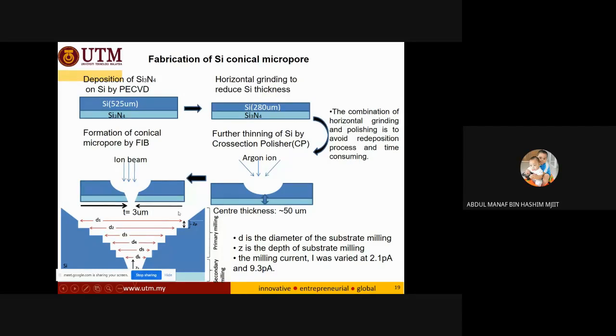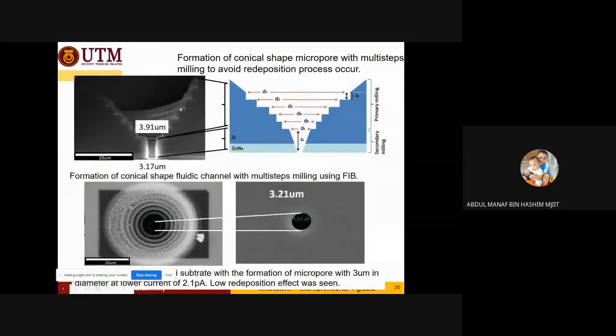Okay, so for the silicon micropore, of course we use FIB here. Let's say we have a sample substrate of silicon and silicon nitride. First we do a thinning and then a polishing, and then we get this structure. Then we proceed with FIB to get the conical shaped micropore. This is an actual fabricated conical shaped micropore. It is a two-step process: first we get the big conical shape, and then finally we make a micro hole here.